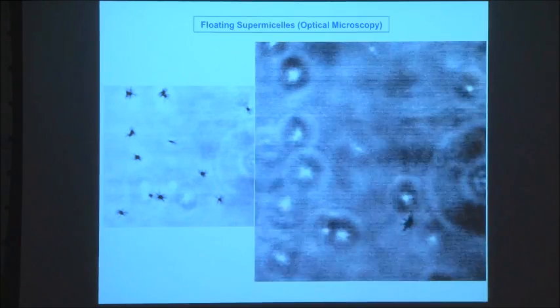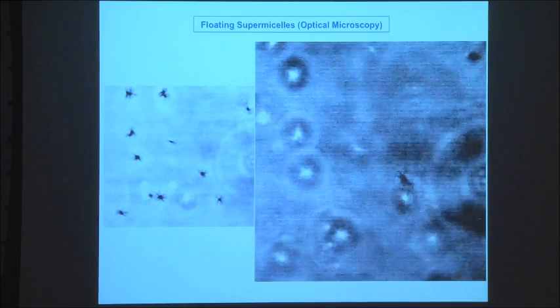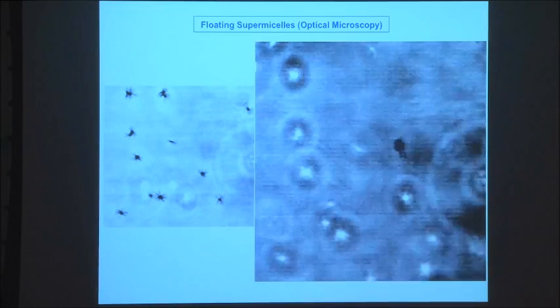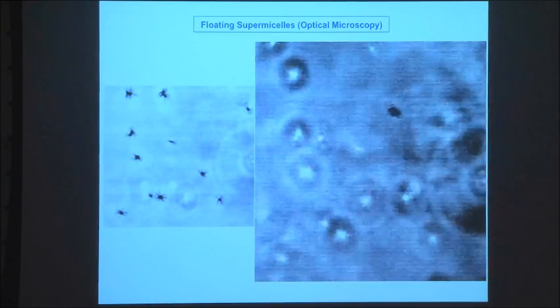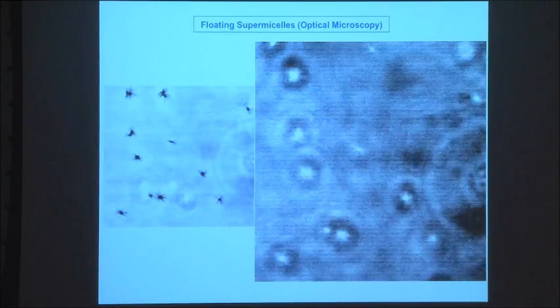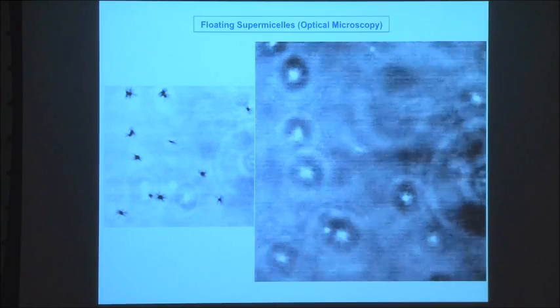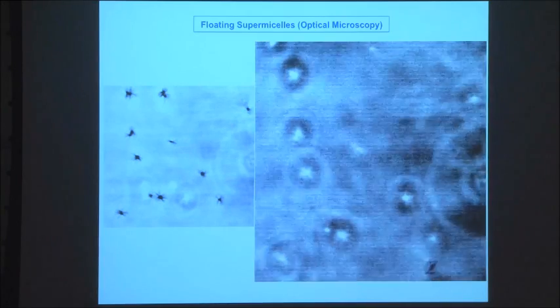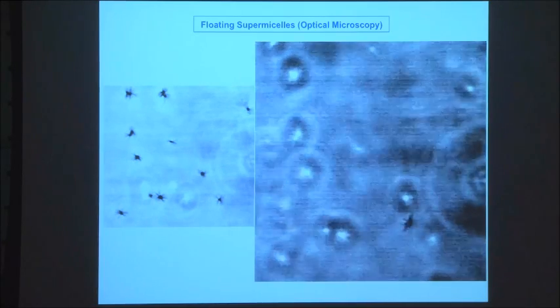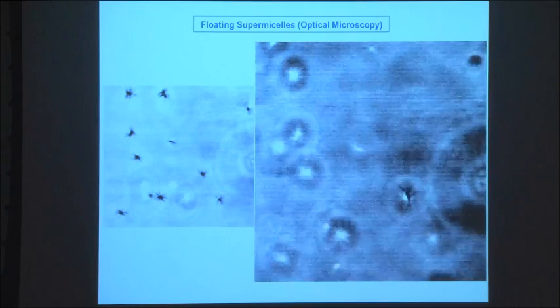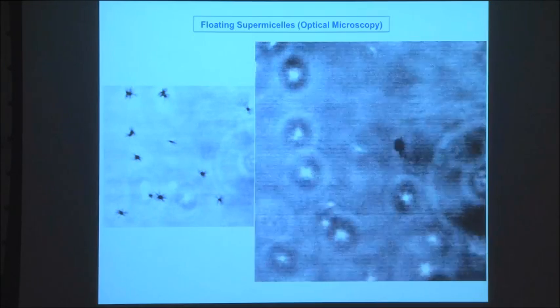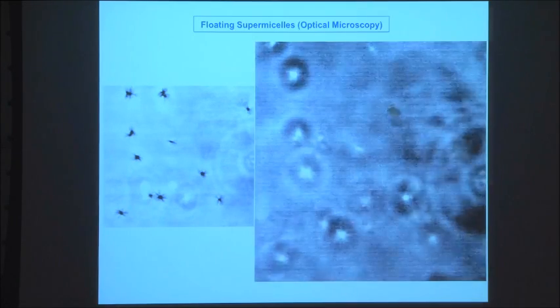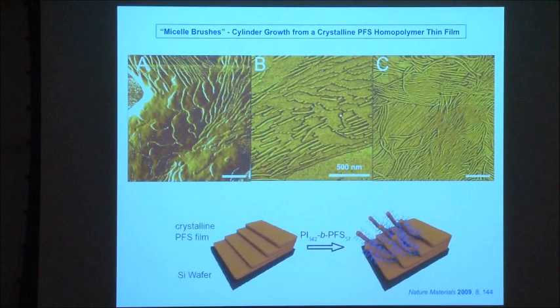So far, all of the crystallization-driven self-assembly I've described involves growth from the ends of cylinders. First, I talked about growing from both ends, and just in that last part of the lecture, I've talked about how you can block one end and make it grow in one direction, which opens up new avenues for making asymmetric or non-centrosymmetric structures. But since this process just works on crystallization, you should be able to take any face of PFS that is crystalline and actually use this process. And this turns out to be the case.